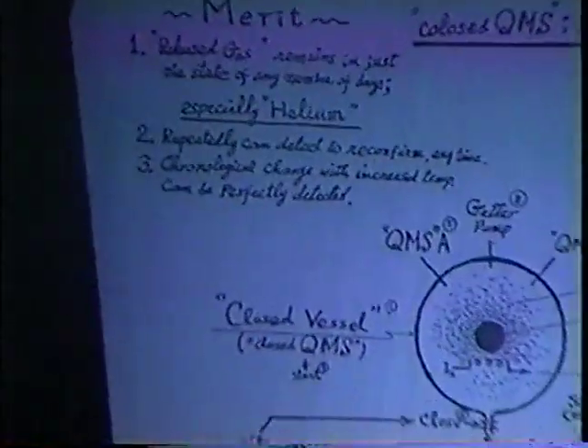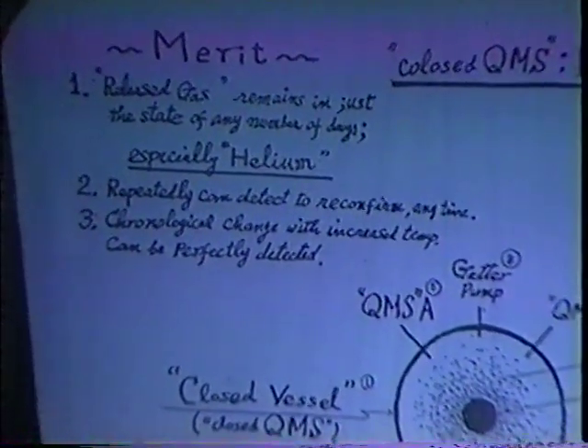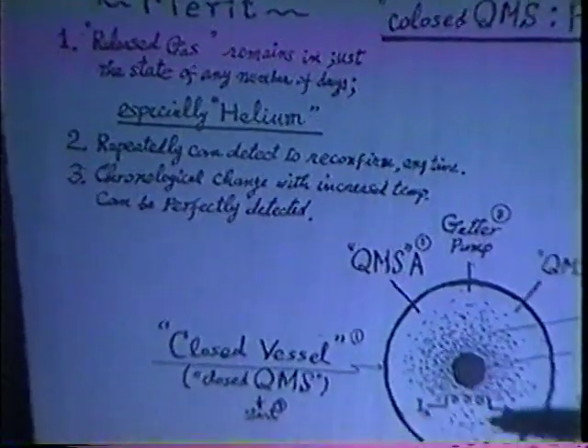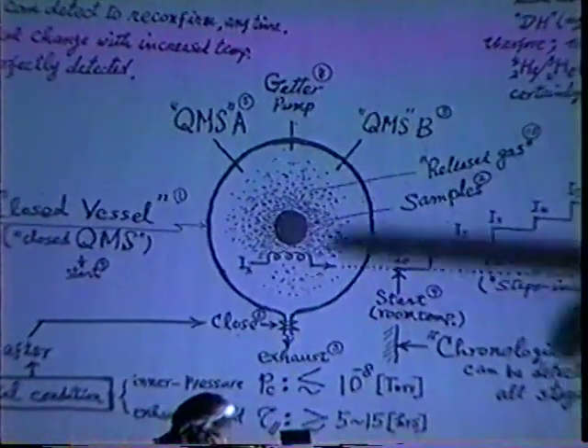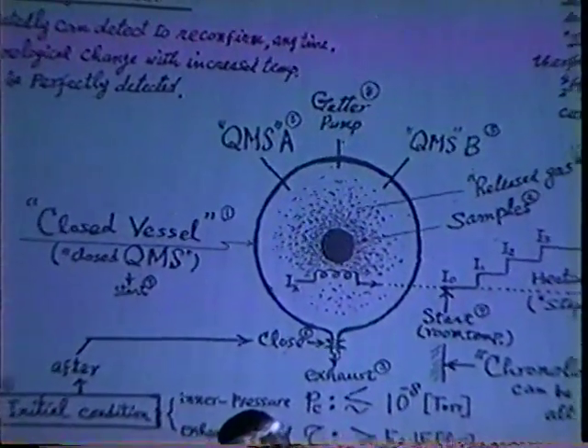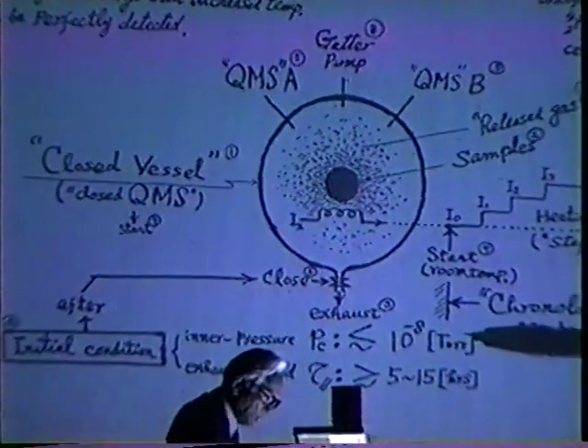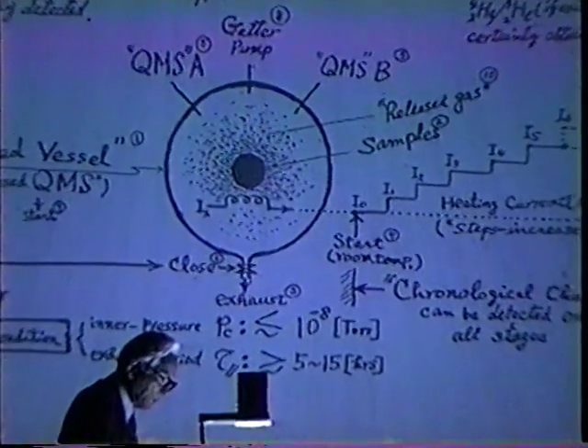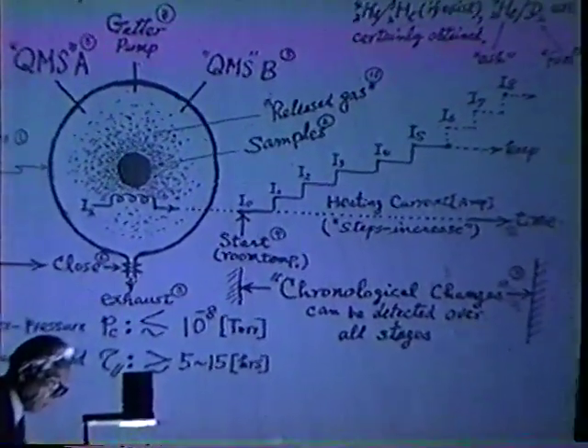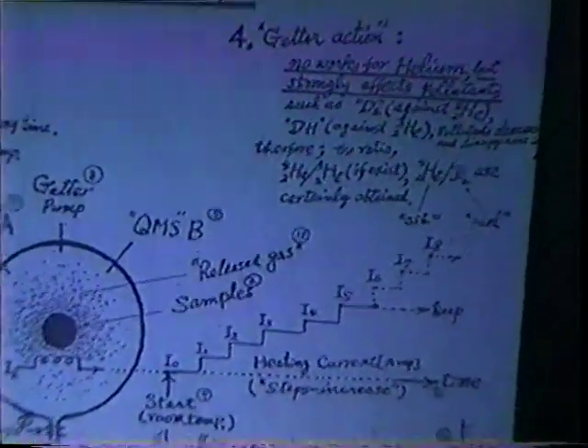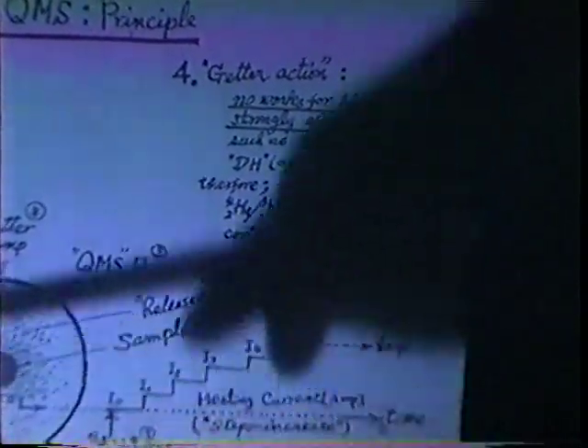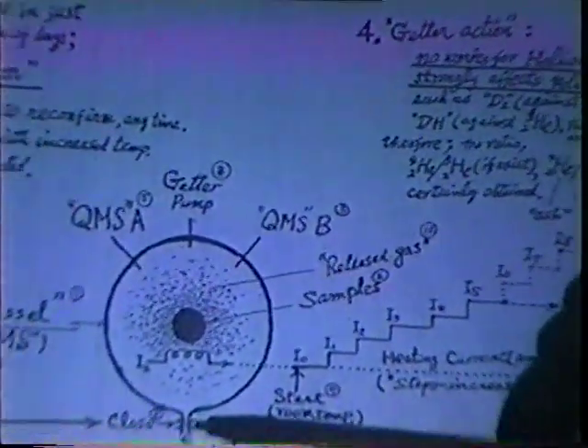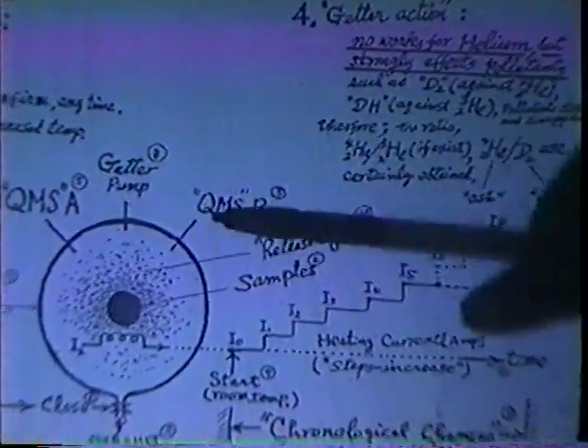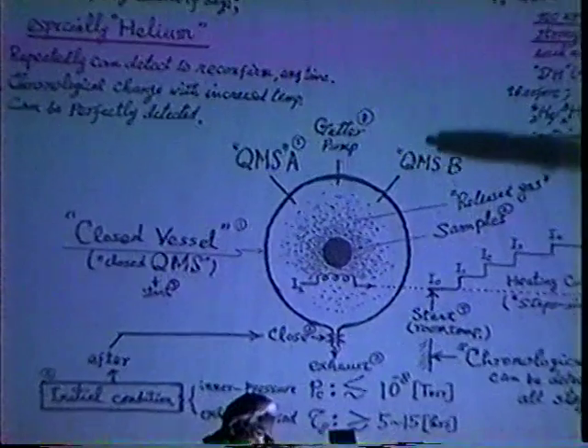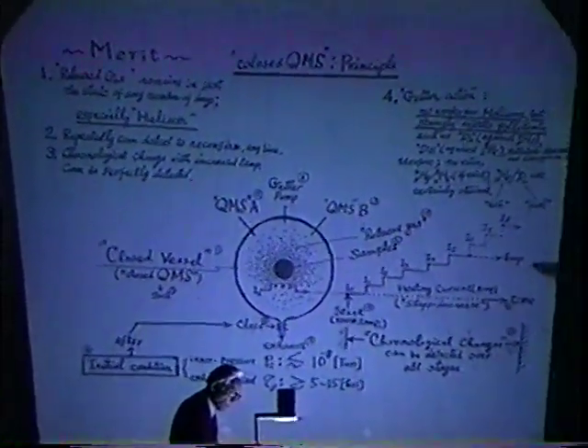And this is the closed QMS principle. The closed vessel holds the sample, and the gas is exhausted to an initial pressure of 10 to the minus 8. Keeping time is 5 to 15 hours, around 10 hours needed, because we must eliminate the pollutant. And then the QMS starts closed, the so-called closed QMS start, and residual gas appears.